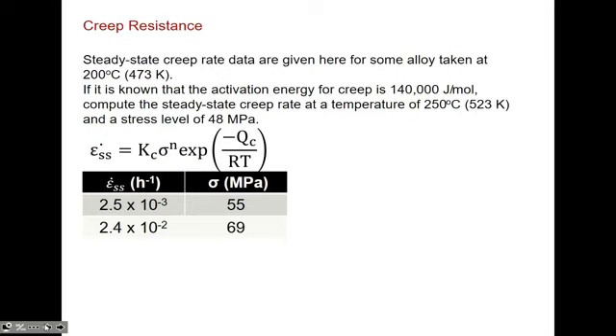Another way is this example here that I'll talk about. So if you're given steady state creep rate for some alloy, some material taken at one particular temperature, here I give an example, 473 K. Okay? If you know the epsilon value, the creep rate, and you know the activation energy, here it's 140,000 joules per mole, you can compute the steady state creep rate at a higher temperature or even a lower temperature, right, and another stress level. So this is what I mean by you can extrapolate this information so that you can test at a lower temperature to guess at a higher temperature what's going to happen. Will it fail